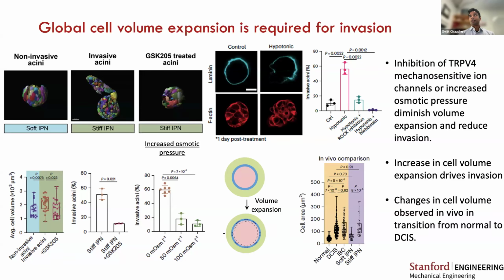Okay, and so you might ask, well, this is just a 3D culture model. Do we know this is relevant in vivo? And of course, that's always a challenge with in vitro models, and there's a limit to what we can do to test the relevance. But what we did was we analyzed cell volumes, using cell cross-sectional area as a proxy for volume, in normal tissue, ductal carcinoma in situ, or pre-invasive breast carcinoma, and invasive breast carcinoma. What you see is as you go from normal to pre-invasive DCIS, you get an increase in cell area similar to what we see when we go from the soft to stiff IPNs. So we do see an increase in area and volume during breast cancer progression.